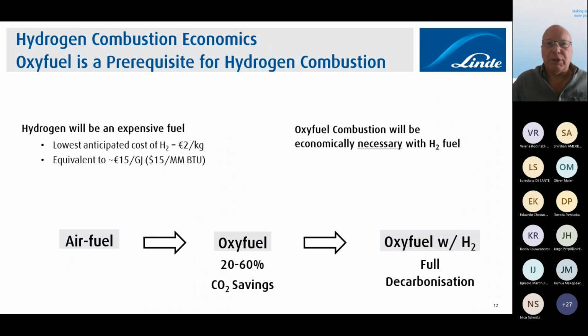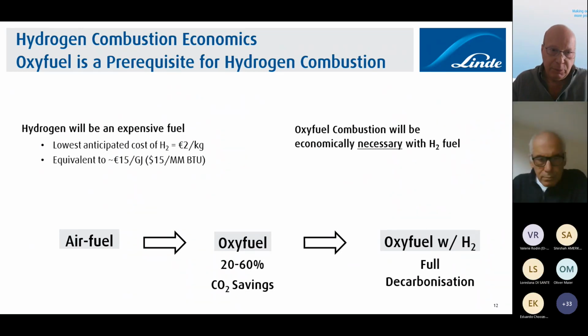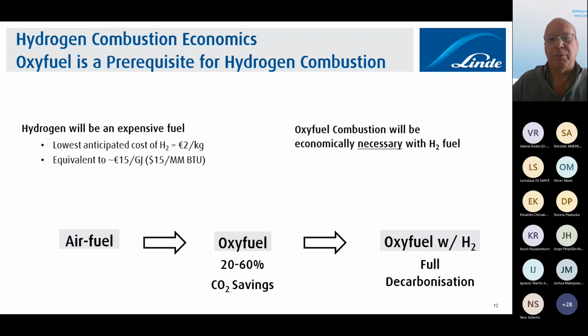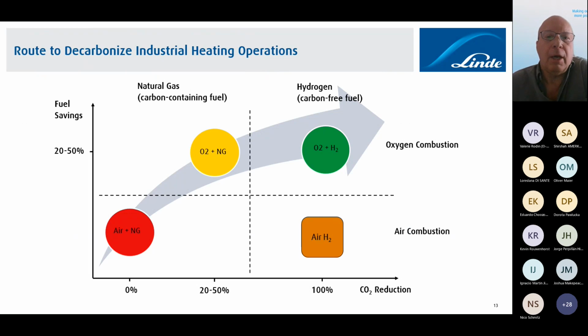However, if we look at the first steps, many times it's not about the reduction, it's about using hydrogen as a fuel. And to do that in an efficient way, we should of course be as energy efficient in our processes as possible to minimize the use of hydrogen. And typically, as we've been working with, is to go from air fuel combustion to oxy-fuel combustion, which would then reduce the need for fuel by 20, 30, 40%. And of course, we will have the corresponding CO2 savings. So that's a way to minimize the requirement for hydrogen in that situation. So we would say that the path is going from air fuel combustion over to oxy-fuel combustion with natural gas, for example, and then start using hydrogen there.